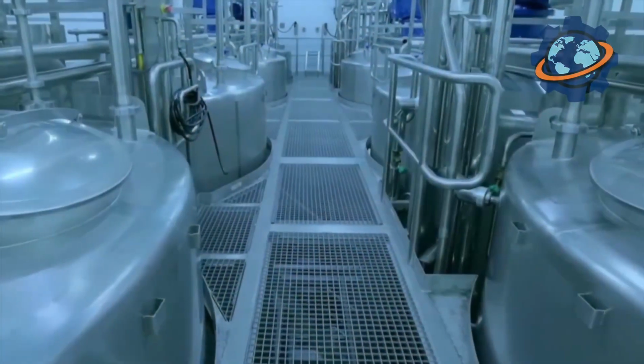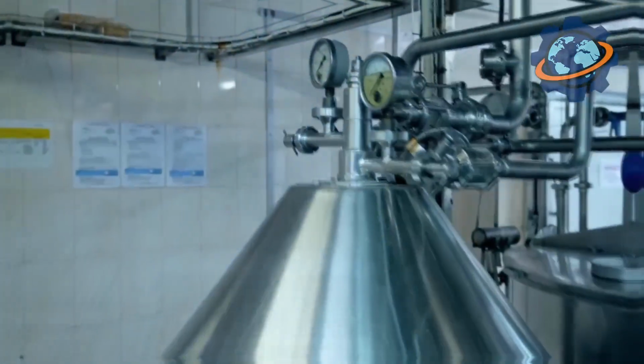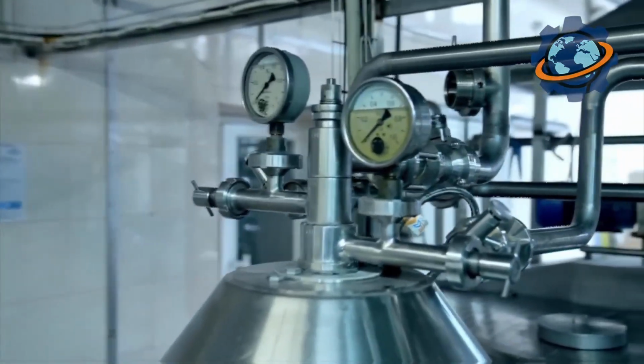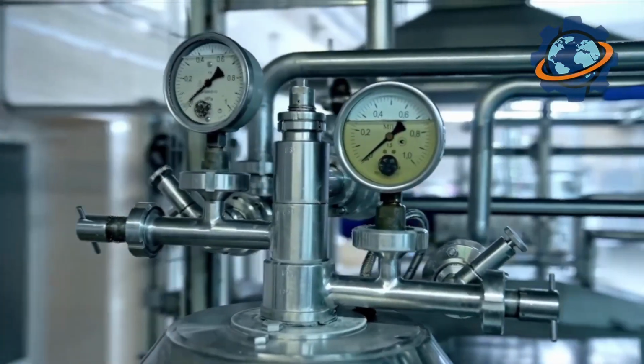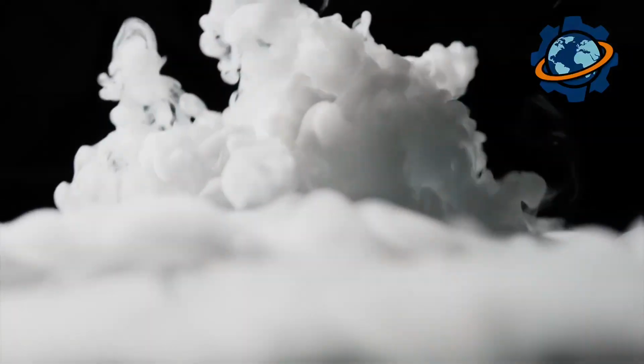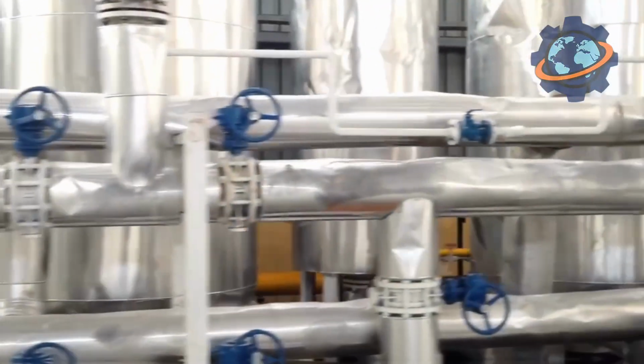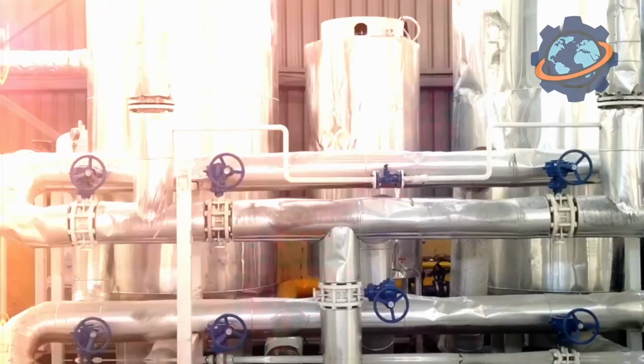They enter a condenser, a special cooled chamber. Temperature in the condenser is around 840 degrees, below the boiling point but above the melting point of zinc. The vapors condense. Drops of molten zinc settle on the condenser walls, glowing orange. Liquid metal flows down the walls and collects in a receiver.